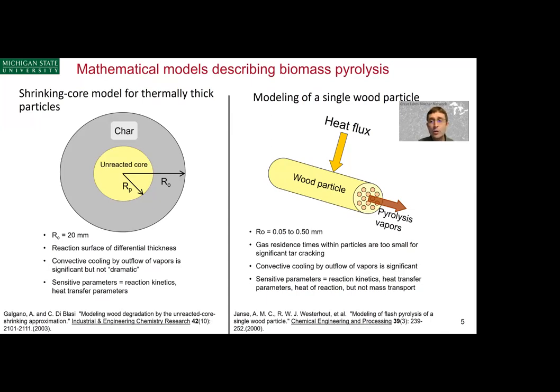When you heat a thermally thick particle, perhaps with a radius of 20 millimeters or more, like the spherical particle on the left side of this slide, as you heat it externally, you get an expanding layer of char that surrounds a rapidly decreasing unreacted core of biomass. As that core reacts, it forms pyrolysis vapors and more char. These vapors then transfer across the char layer to eventually vent out into the space between particles—that's the pyrolysis vapor we collect and condense to make bio-oil.